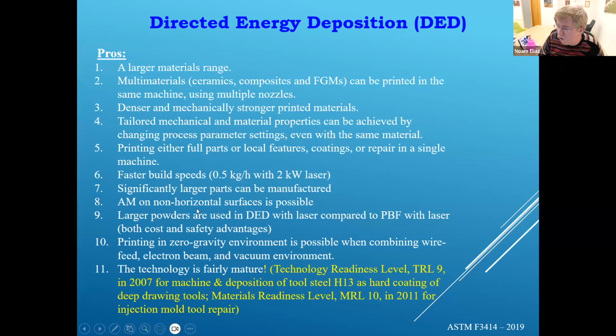You can print on non-horizontal surfaces. For instance, you saw the blades. You use larger powders in DED with laser compared to powder bed fusion with laser, which means that it's safer and it's cheaper. You can also use wire in a vacuum atmosphere. NASA is printing in a zero gravity environment, and they have also made modifications in-house.